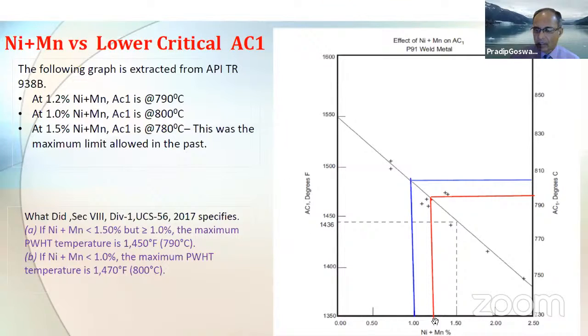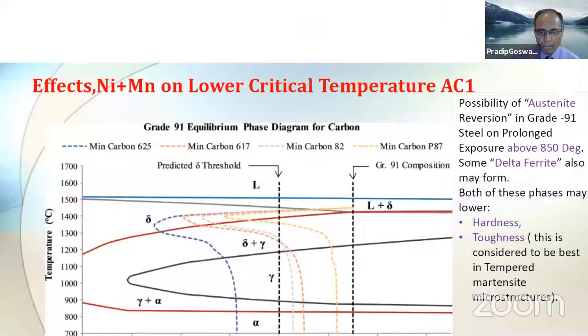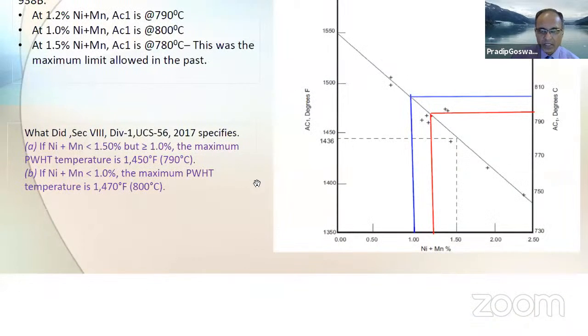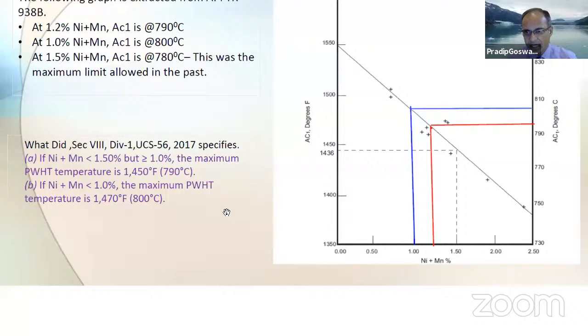So typically, when this content is controlled to between 1 to 1.5%, the mills and the fabricators get an additional allowance of 20 to 30 degrees centigrade with respect to the maximum tempering or maximum post-weld heat treatment temperature, which is quite significant with respect to many properties, many problems, which we'll talk about later. Staying on this slide, I hope I have made it clear what the typical AC1 temperatures are at various levels of nickel and manganese content one can expect.